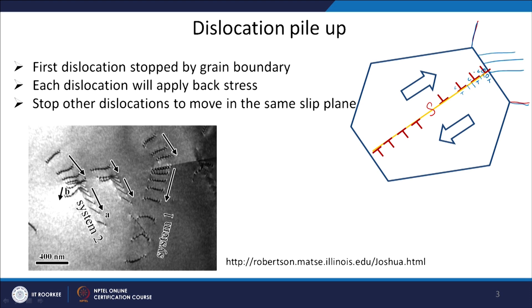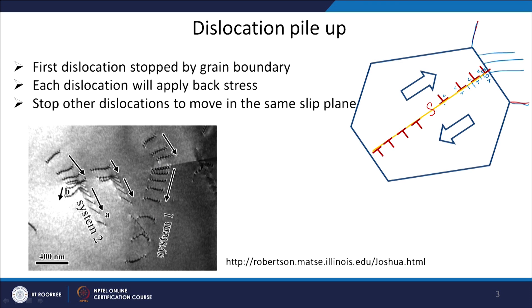Slowly you will see the pileup is there, but slowly you will also see that the dislocations will stop much before the others. For example, this particular dislocation now sees the strain field of all three dislocations together. Because it sees a larger combined strain field, it will stop much before the pileup. This is how the dislocations get arranged.